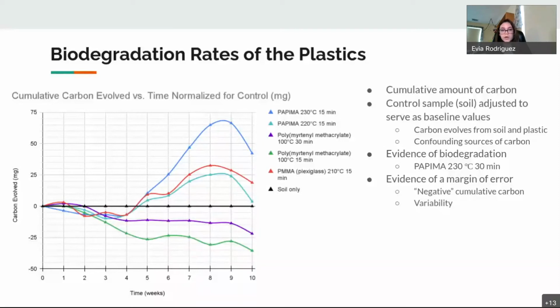And there's also a margin of error that I need to point out here. That is because there's variability in my experiment due to the lack of replication I used. I only did one jar of each sample. So because you can't exactly have a negative amount of carbon evolving from a jar, it can be assumed that the negative values here are variable amounts of carbon that evolved from the soil rather than amounts of carbon that evolved from the plastic. So the main thing with this graph, as I mentioned, is that there's more evidence of biodegradation. The most evidence of biodegradation is in the PAPIMA sample, highlighted in blue.